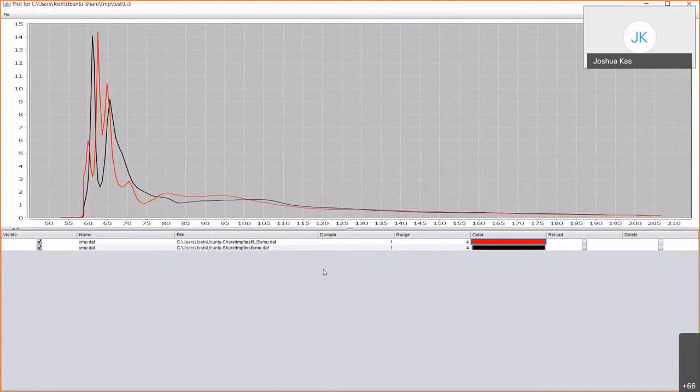So you can do something similar to what you're doing with convergence of FMS and SDS, where you start adding unique potentials around the absorber, right? So if you have some oxygen that's right next to the absorber, say it's a metal with ligands on it, and then the ligands are quite large and have lots of different oxygens in them, you want to represent the oxygens next to the absorber pretty well. You don't really care so much about the ones that are out further.